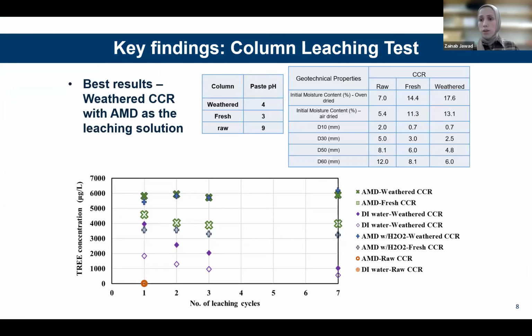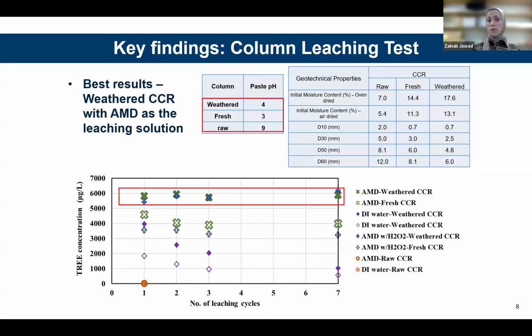So for our key findings, the first important finding was that a combination of weathered coarse coal refuse with AMD as the leaching solution gave the best results. Weathered refuse had the highest leaching potential when we compare it to the other two types. And there were 3 reasons behind this finding. The first reason is that pyrite oxidation has already taken place within the weathered refuse, and RE compounds were made readily available at the surface of the refuse.